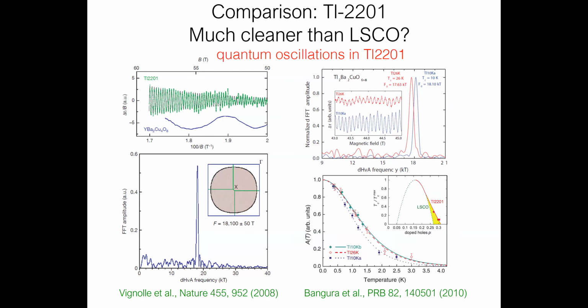So, one thing that we wanted to do was to look at other materials. That was LSCO. We wanted to look at other materials which can be overdoped. And unfortunately, in the cuprates, there are only a couple of materials that you can take easily to very high doping and watch the superconducting dome disappear. One of them is LSCO, and the other one is thallium-2201. So this was already known to be fairly clean, at least relative to LSCO, by the fact that you could see very nice quantum oscillations, which cannot be seen in LSCO as far as I know at the present time. Nobody's seen them. So the expectation was that this is significantly cleaner.